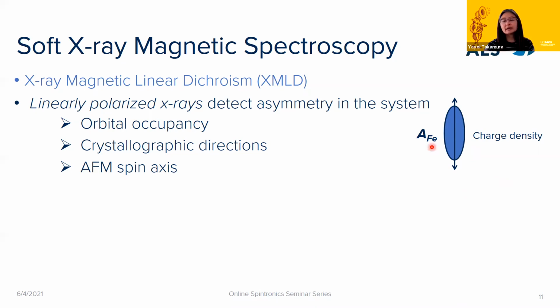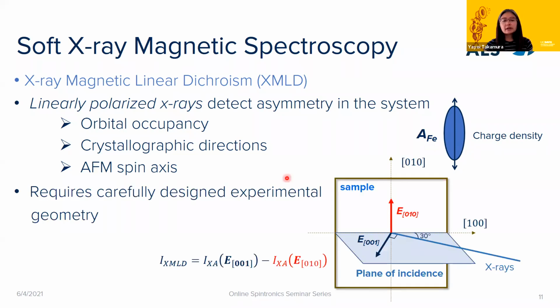Again, we need to carefully design the experiment geometry in order to rule out any of these other effects. For example, if we're looking at one of our thin films, then we need to change the polarization direction from vertical to horizontal, which will probe along, say, the 0, 1, 0 direction, which is in the plane of the sample, and then 0, 0, 1, which is out of the plane of the sample. Because if we think our spin axis might be lying in plane, and we want to see that, then we'll use this other geometry. And so we're along the same general family of crystallographic axes.